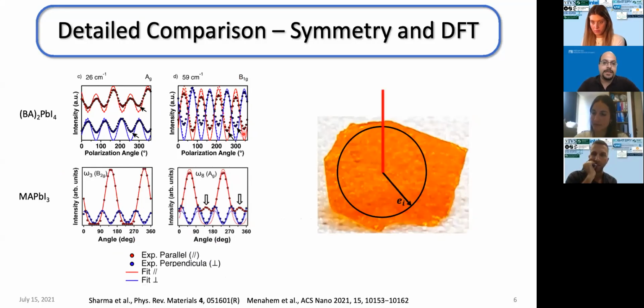sample with linearly polarized light, and then we collect the backscattered light, scattered either parallel or perpendicular to the incident polarization, and we follow the modulation of the intensity of each peak as we rotate the incident polarization, which is what you see here: the modulation of intensity of each peak as a function of the polarization angle, which is the x-axis. The red curves are the parallel configuration and the blue curves are the perpendicular configuration. And by fitting it to a model, which is the solid curves here, we can extract the mode symmetry.